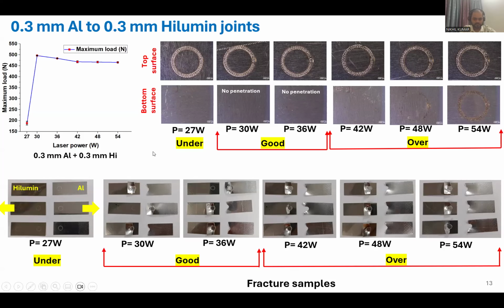So what is happening here? This is 27-watt laser power. You can see there is no bottom face penetration at 27 watt, but the weld strength is very low. You can correlate this with the picture on the bottom left. This is interfacial failure: the two materials separated after the lap shear test.